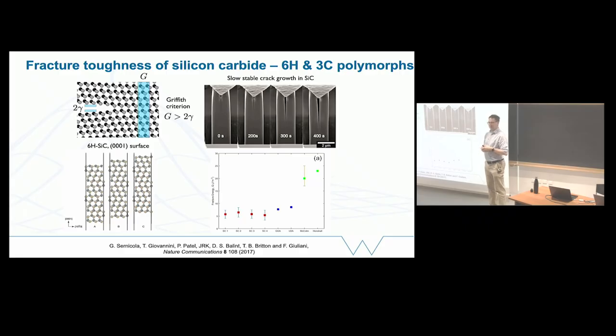The reason that you can estimate that reasonably clearly is that it's really driven by a long-term thermodynamic energy balance. What happens when you create a crack is you make two new surfaces and you relieve strain or stress, some elastic energy, from some region ahead. So there is this 100-year-old theory of fracture mechanics that tells you that it's favorable to propagate when the amount of elastic energy that you release exceeds the cost of creating two new surfaces. So in order to make a prediction about that, we need to do DFT calculations of surface energies and of elastic properties. This G here is a function of the elastic properties, which we can compute.